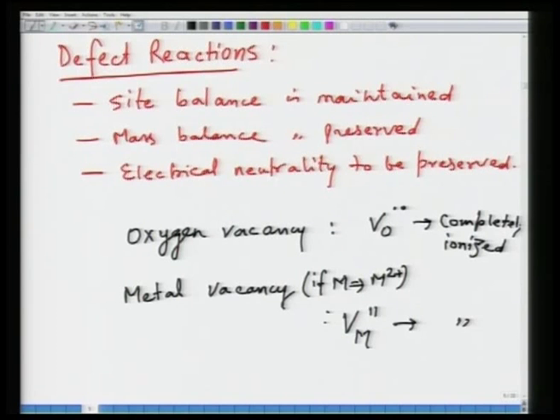And in this case, since we are treating oxides as the main materials in this defect chemistry module, we will treat oxygen vacancy as VO double dot, assuming that it is completely ionized, and a metal vacancy, if metal was M2 plus, then it would be VM double dash if it was completely ionized. If the valence of metal is different, then it would be VM single dash or triple dash or 4 dash, depending on the valence of the material.